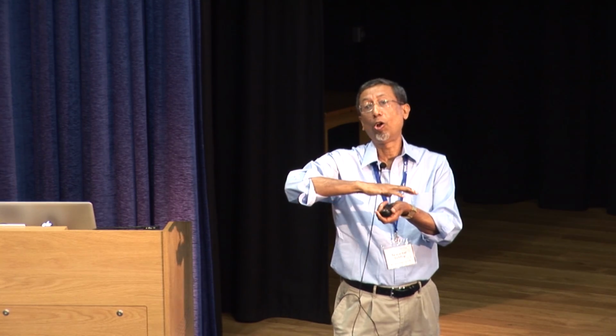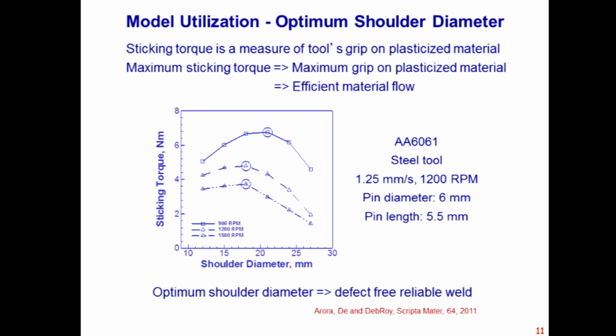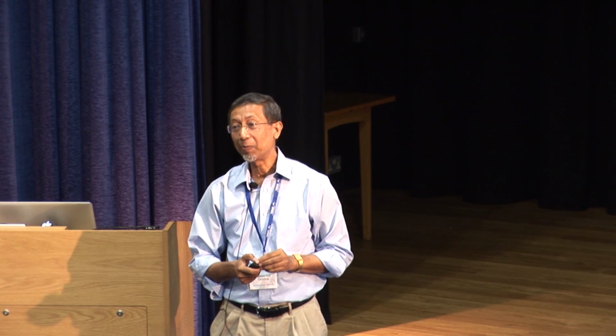One of the things that cannot be measured very easily is the sticking torque. Sticking torque gives us the grip of the tool on the plasticized material, and that dictates how good the flow pattern is going to be. And we show here that there is an optimum shoulder diameter for each operating condition where the tool's grip on the plasticized material is maximum. And it has been shown that if you do not use an optimized tool shoulder diameter, then there is a good chance you will get a defect in the weld. So structurally sound, reliable welds can be obtained using computer models.